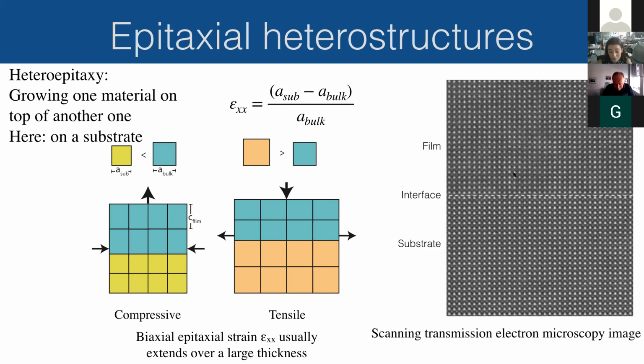In particular, epitaxial growth means that if you look at the atoms of the substrate, then the atoms of the film are going to fall exactly in registry with them. This is an image of a real film, one that I grew, and you can see the white dots are the rare earth cations of the perovskite oxide substrate, and similarly in the film. You'll have to take my word for it, but that's the interface, and you see there's almost no difference between the substrate and the film. This is real heteroepitaxy. It means that for all intents and purposes, the film is like a single crystal. It's just very thin.